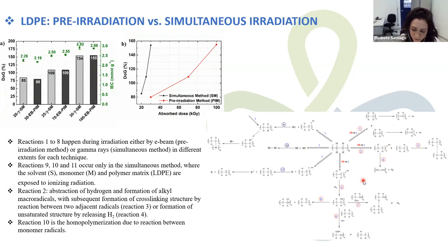The main reactions involved in grafting occur as a consequence of the radical formation. The reactions involved in both methods are grafting, cross-linking, unsaturation, and degradation of the chain. The reactions from the formation of radicals to reaction 8 are common to both methods, I mean, to electron beam or gamma radiation. Okay, the reactions 9, 10, and 11, of course,